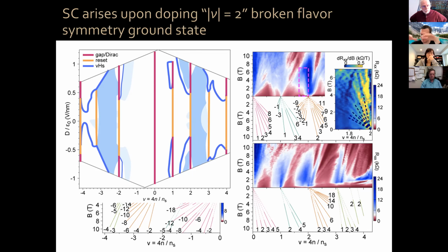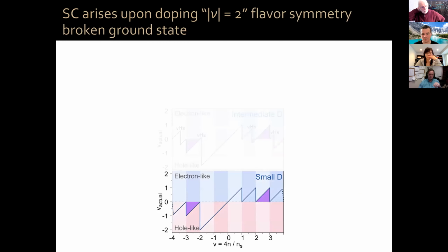You have 2 Fermi surfaces, but hole doped. And then you go through 0 and then to electron doping. But you can see superconductivity, and that tells you that superconductivity happens when you dope with electrons or with holes that 2 Fermi surface state, okay? That 2 flavor, 2 empty flavors state, okay? And that's what we believe is happening.